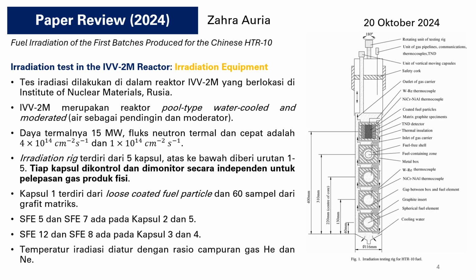We'll move to the irradiation equipment. Here is the irradiation testing rig for HTR-10 fuel, and this irradiation test was carried out in the IVV-2M reactor that is located at the Institute of Nuclear Materials, Russia. The IVV-2M reactor is a pool-type water-cooled and moderated reactor that has a thermal power of 15 megawatts and thermal and fast neutron flux of these numbers. The irradiation rig consists of 5 capsules. From top to bottom they are named capsule 1, capsule 2, and so on. Each capsule is controlled and monitored independently for the gaseous fission product release.